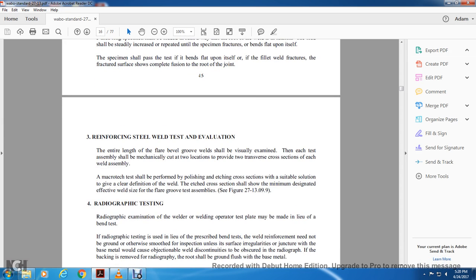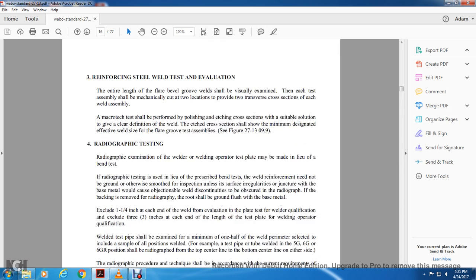Three. Reinforcing steel weld test evaluation. The entire length of the flare bevel groove welds should be visually examined. Each test assembly shall be mechanically cut in two locations, providing two transverse cross sections of the welded assembly. The macroetch test shall be performed by polishing and etching the cross section with a suitable solution to give a clear definition of the weld. The etched cross section shall have the minimum designated effective weld size. Flare groove test assembly, see Figure 2713-09.